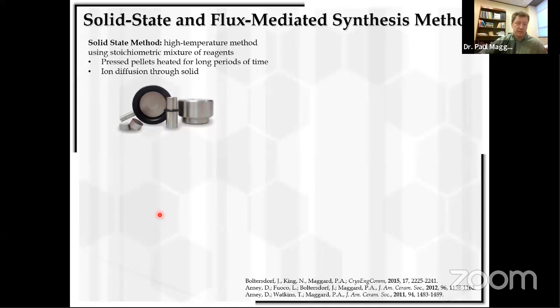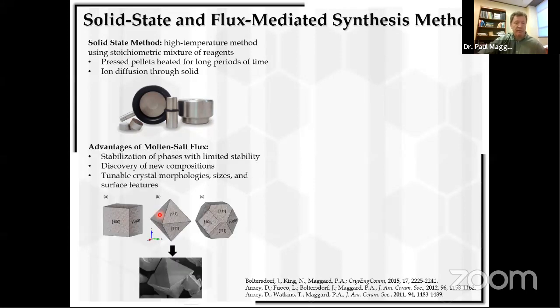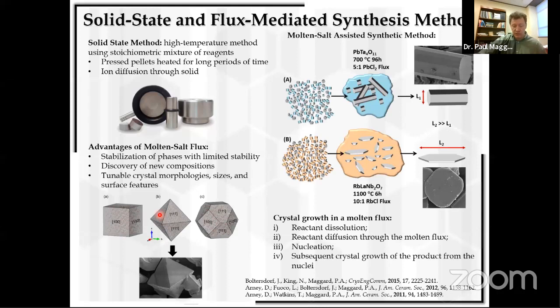as well the morphologies, because most solid state structures are anisotropic, meaning that when you excite electrons within them, their mobilities in different directions are going to be higher in some crystallographic directions, lower in other crystallographic directions. For example, if you have a layered material versus a three-dimensional material.